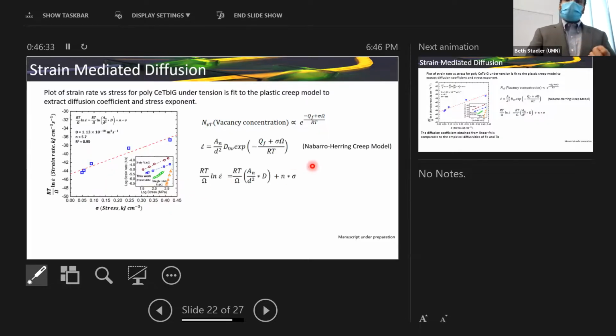Now, moving a step forward, one of the primary mechanisms that controls the diffusion of vacancy is called the Nabarro-Herring creep model. We write down that equation, which is essentially a strain rate, which is a function of the grain size, or diffusivity constant at infinite temperature. Then you have the activation energy, the strain terms, and the temperature. Now we rewrite it to make it linear, and we add this pre-exponent factor, which will allow us to capture the different kinds of diffusion processes that are happening in the material.